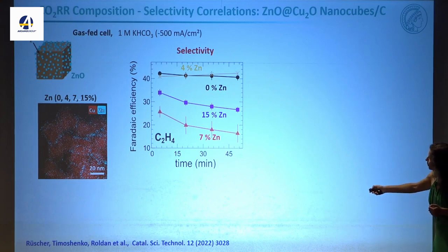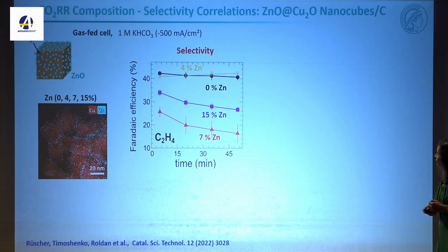So we created these copper oxide nanocubes, and then we have this zinc on the surface. And you can see here that the Faradaic efficiency versus time depends on the amount of zinc that you have in these copper zinc structures. If you have only a little bit of zinc, you get very nice Faradaic efficiency for ethylene, which we wanted to make, and it's stable. But if you start putting too much, you see this deactivation.